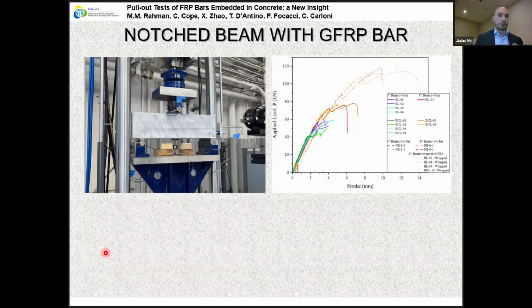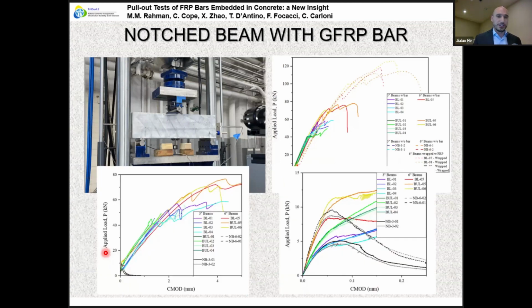We redid this test also for the second set of bars, the ones that are ribbed. And the interesting thing is that when you do this test with this new bar, you don't see the load following the plain concrete. You see that it actually goes off completely from the beginning. And the reason is that the ribbed bars have a much shorter bonded length than the sand-coated bars, so they pick up the load quite quickly compared to the sand-coated bar.